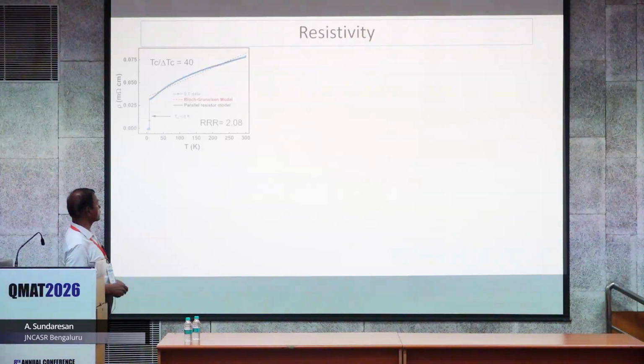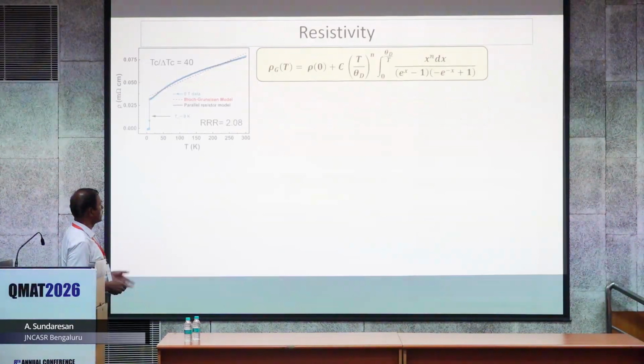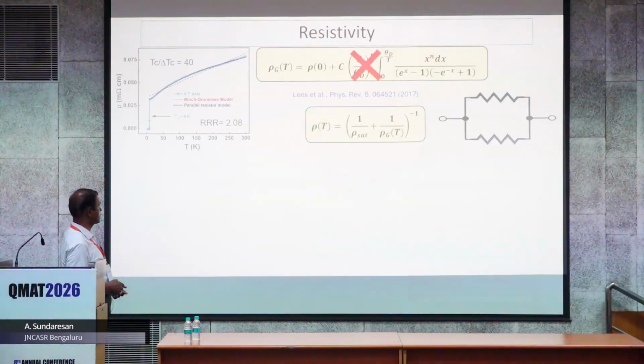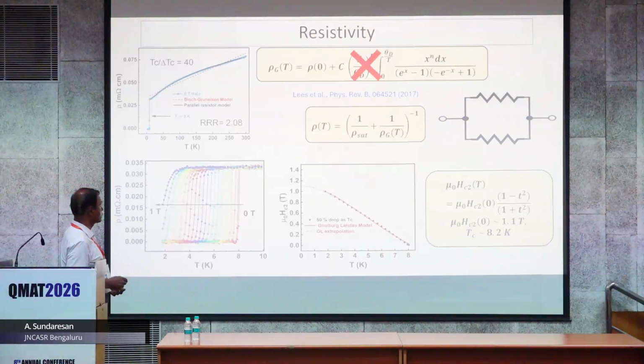Then we look at the normal state resistivity, and we try to analyze with the Bloch-Gruneisen model, but it doesn't fit very well. So we need to take the saturation aspect of the scattering, and that fits reasonably well, as shown in this parallel resistor model.